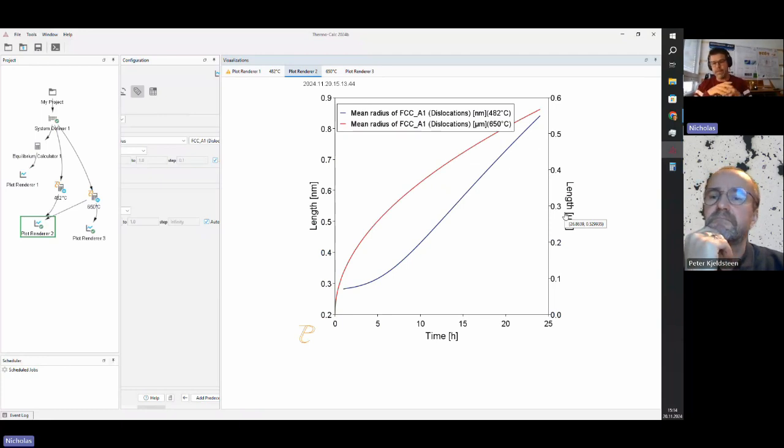Again, it's one of these things that calculations can probably just help a certain amount, right? Because at the higher temperature, you might also have grain growth. You might have other things that are happening that are not desirable, and you might also have to be careful about overaging, right? So that the precipitates don't grow too big, so that they'll no longer have that strengthening effect, right? So yeah, but basically that's an example of a nucleation and growth calculation, right?